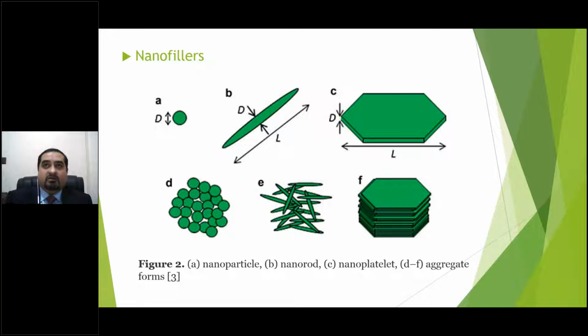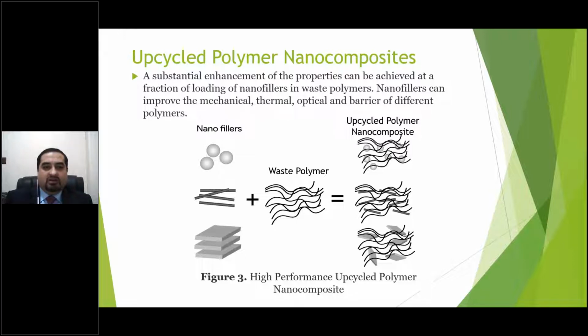So our goal is to make sure that once we incorporate the nanofillers within our polymers, we get the least amount of aggregates or the assembly of aggregates or the agglomerates, as they are known. Unfortunately, we cannot eliminate them, especially once we try to move towards higher weight percentages. One of the points that is now being realized by scientists throughout the world is that if we try to incorporate more and more nanofillers, or higher weight percentage of them, then aggregates form in quite large quantities. So what we can do in upcycled polymer nanocomposites is try to incorporate these nanofillers into our waste polymer and make sure that they remain separated. The aggregates don't form. This is our basic requirement for any method that is being used. It should ensure that, and this is the goal of this research.